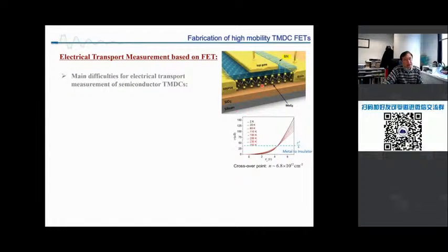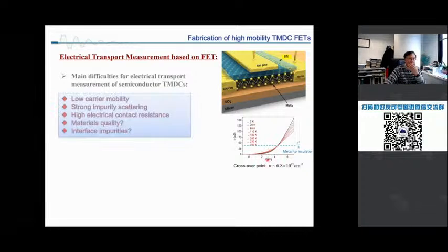So the field effect transistor structure is pretty simple. Basically, you need a source and drain electrode connection here, and then you apply a gate voltage through a dielectric material, for example, boron nitride. And then you will see this on-off characteristic. And there's a cross point, the so-called metal-insulator transition. In this kind of region, when you increase the carrier concentration to the right side of this point, the material's behavior is metallic. On the left side, it's insulating behavior.